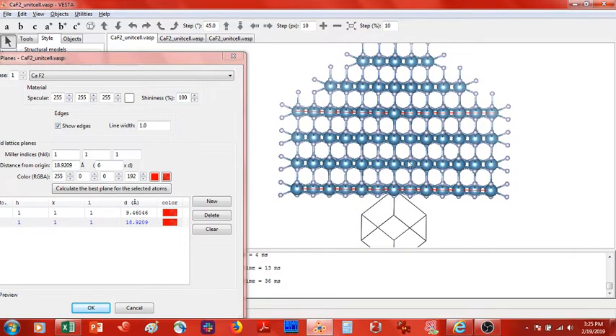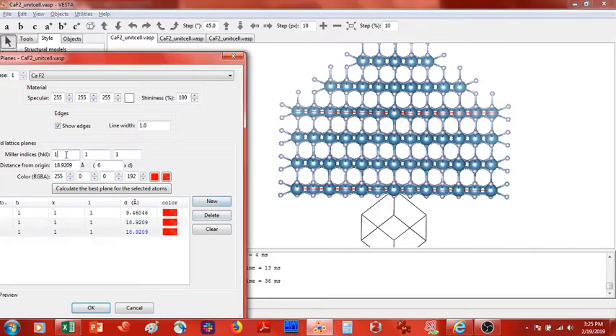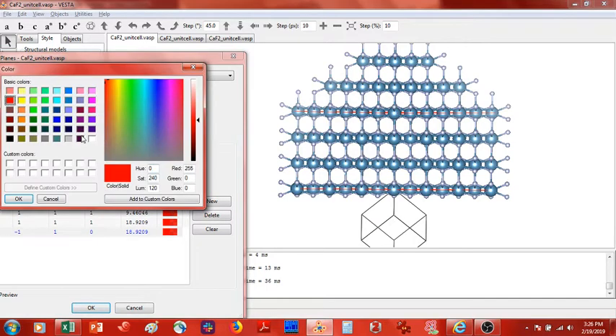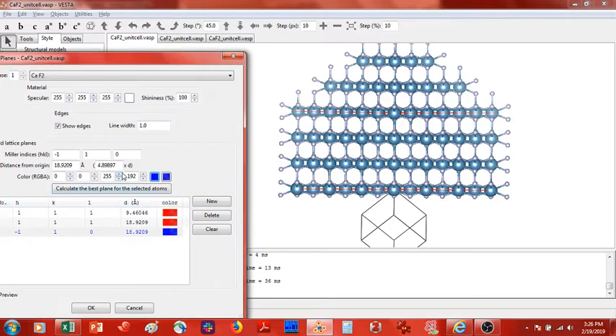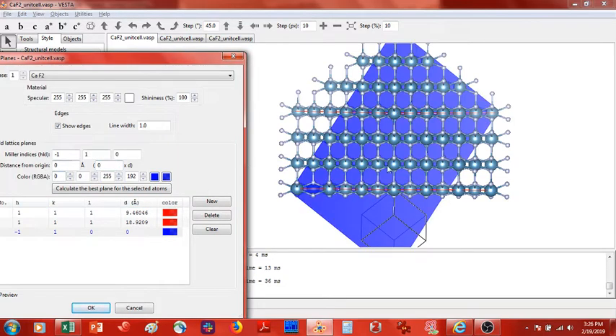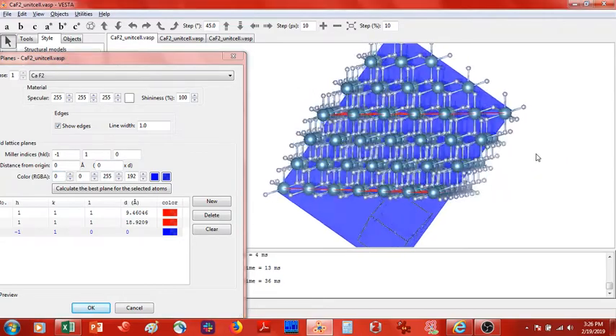Now I'm going to reorient the crystal so that the 111 plane is how I had originally cut it. The next thing I want to do is define a lattice plane that is perpendicular to the 111 unit cell. I happen to know that the (-1 1 0) plane is perpendicular, so I'll change the color to dark blue for contrast and put the distance at zero.